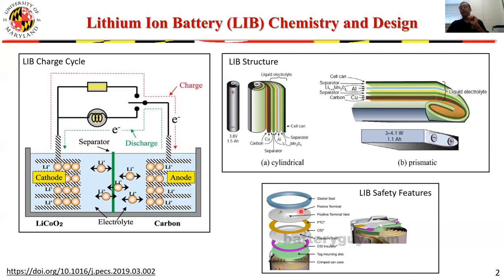Now, one last safety element that is typically incorporated in every battery is called safety vents. They typically are a part of the top cap assembly of the battery. What they do is, they're basically a weakened structure of the steel can. They are burst disks. They open up when the pressure inside the battery increases above critical values. They don't prevent thermal runaway, but they do help prevent rupture or catastrophic rupture of the steel can of the battery, which may result in formation of fine shrapnel. So this is something that safety vents successfully prevent.